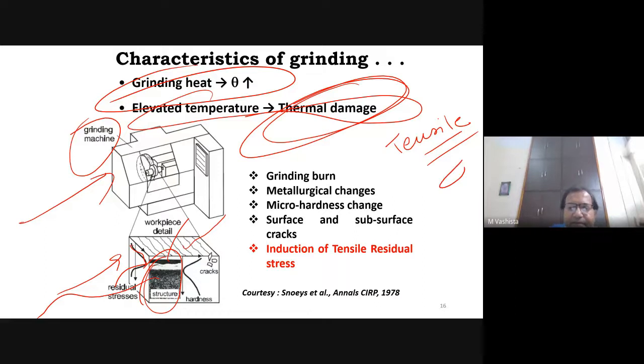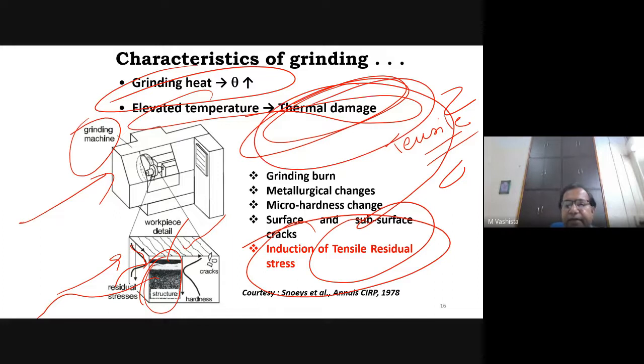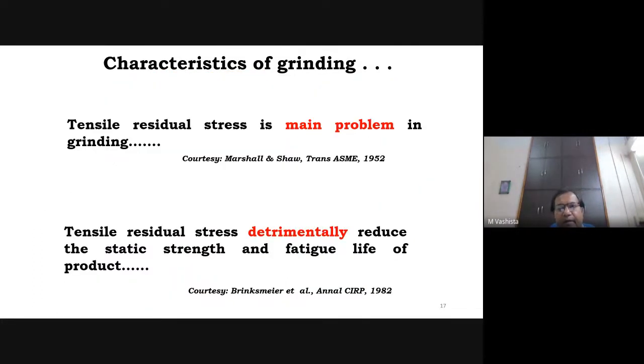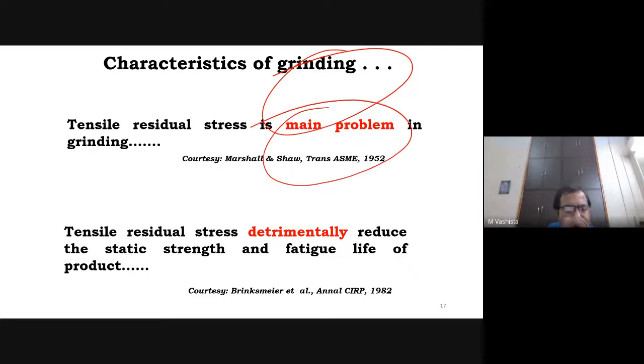Cracks will be there. And now we came to know that because of the heat, thermal damage, tensile residual stress will be generated. Hence, to assess these, we have to characterize the material. Various scientists who work in the area of assessment of residual stress have clearly declared that in grinding, tensile residual stress is typically generated, and that is the main problem in grinding. Because the induction of tensile residual stress will detrimentally reduce the static strength as well as fatigue life of the product.